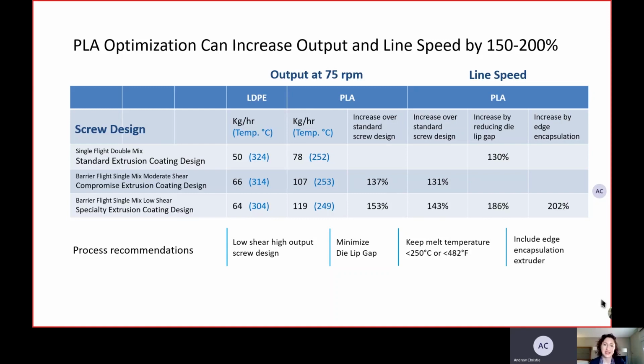So the recommendations are: invest in that low shear, high output screw design for PLA, minimize your die lip gap, keep your melt temperature under the critical 250 C or 482 degrees Fahrenheit. And if you have edge encapsulation, include the edge encapsulation.